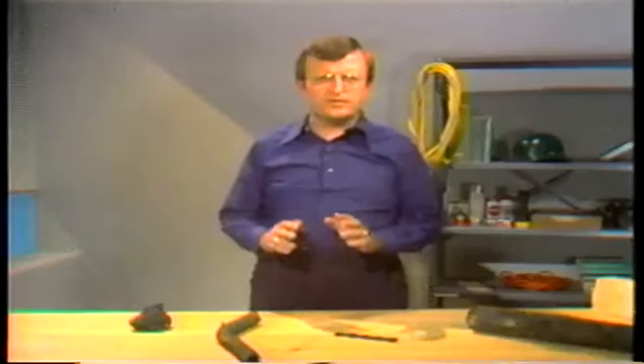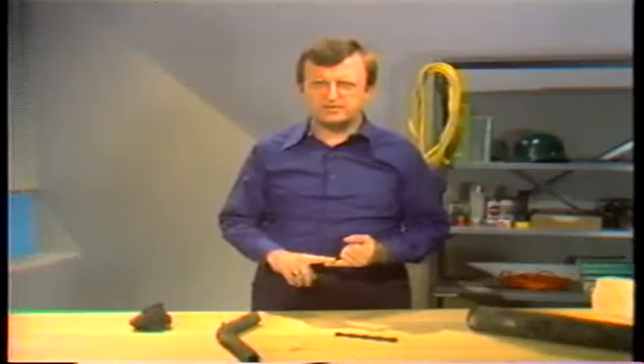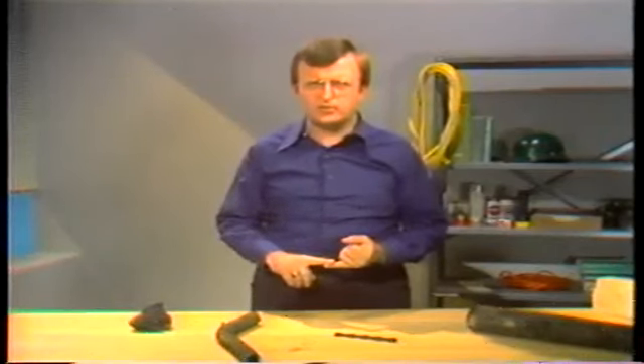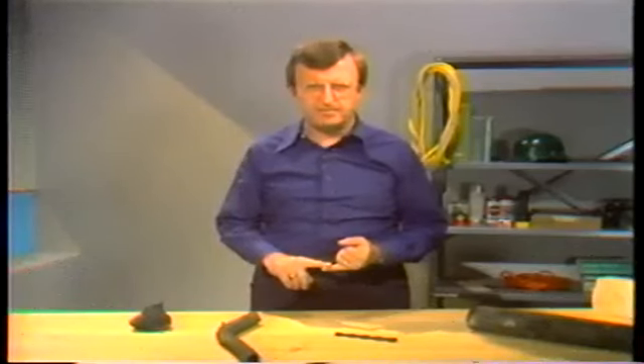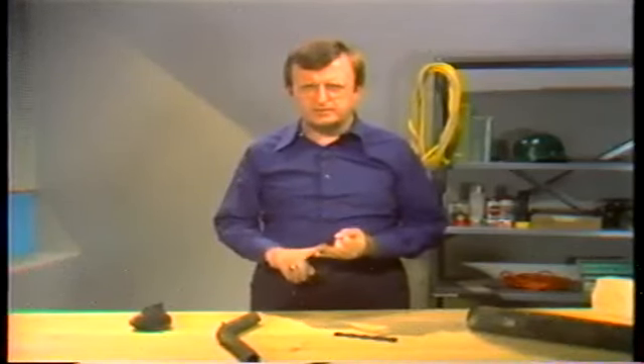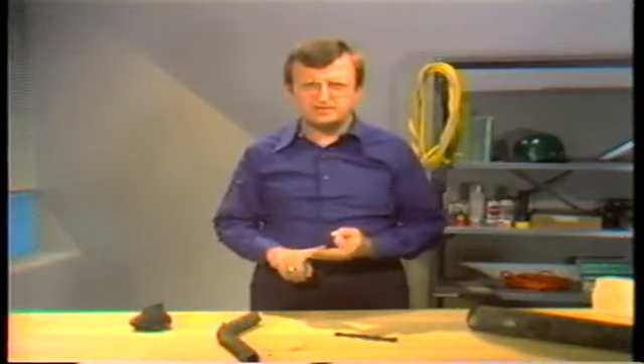We've gone over 4 potential problems with the metal in the water wall tubes. Surface deterioration, including erosion, corrosion, pitting, cracking, and scale formation. Failure of previously repaired areas. Failure of construction welds. And leaks.